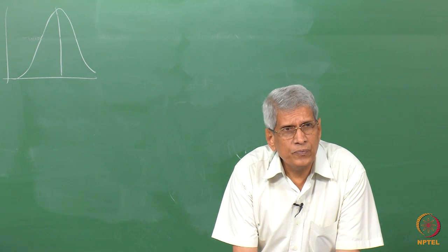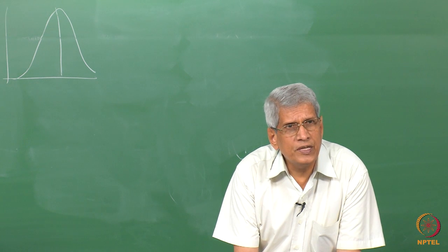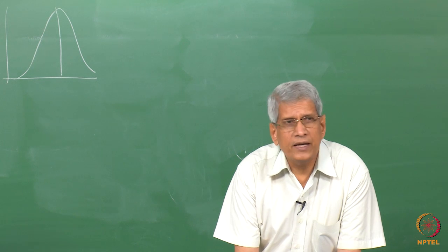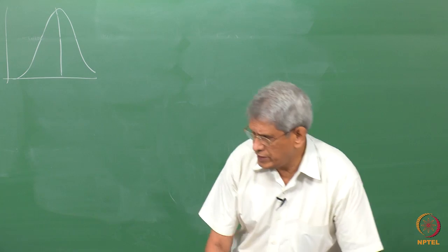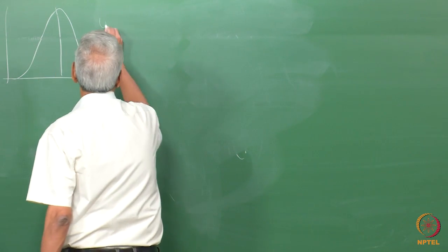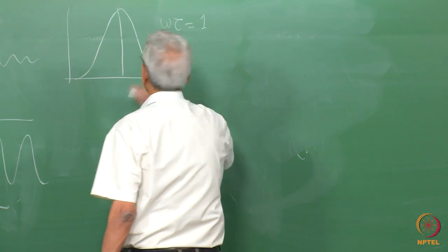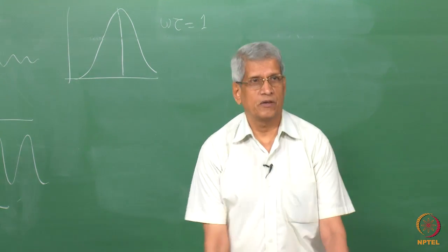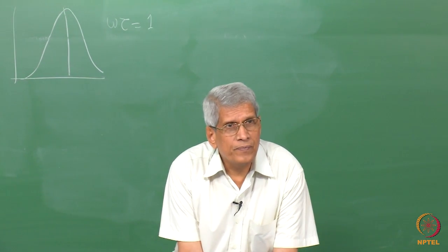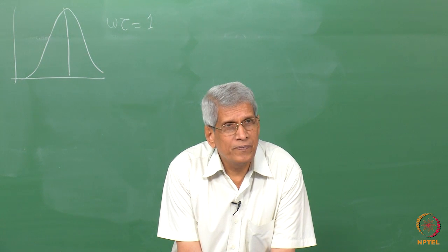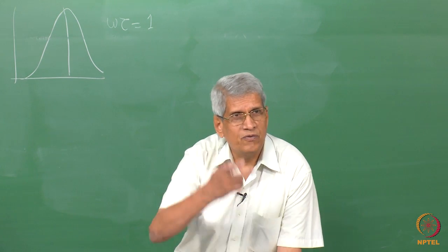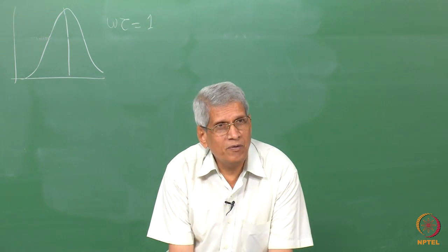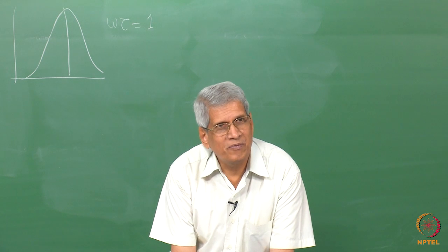Now, this frequency can be related directly to the jump rate also. So essentially, omega into tau, at delta max, equals 1. This is how the expression will be. Okay. I do this experiment at another temperature, just varying this frequency. Then what will happen? The frequency at which the maximum of delta occurs,